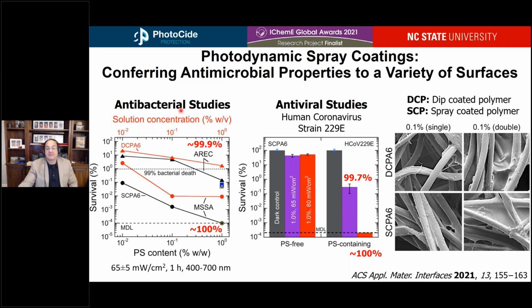Those were antibacterial studies. In terms of antiviral studies, if we take a look at a common cold human coronavirus, not the one that causes COVID-19 disease, but a surrogate that is approved for use in biosafety level 2 facilities that we have available to us. You can see that in the absence of our photodynamic agent, we have 100% survival or infectivity of the human coronavirus. However, in the presence of the fibers that have been coated with our photodynamic agent, we're able to obtain anywhere from 99 to 100% inactivation of human coronavirus with just visible light illumination. Again, that can happen with either the spray-coated or the dip-coated materials.